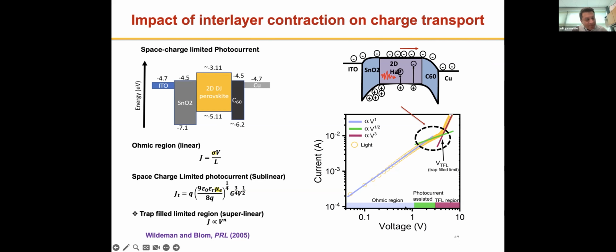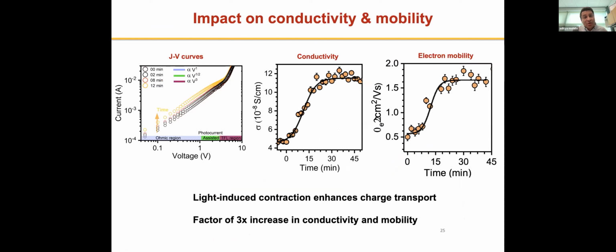What you end up getting, if you look at your current-voltage curves under illumination, is a saturation region, where otherwise the curve would have been quite linear and increasing. You wouldn't see this in the dark. So the current increase slows down, and it changes to a dependence of about V to the power of a half, as opposed to V to the power of one in the dark. Using this idea, you can extract the mobility and also the conductivity from the linear region, which is the ohmic region of this curve. If you perform these measurements as a function of light soaking, just like we performed the structural measurement, you see that after about 5 to 10 minutes of photoexcitation, you start to see jumps in your conductivity, coming from the ohmic region, and also in the electron mobility.